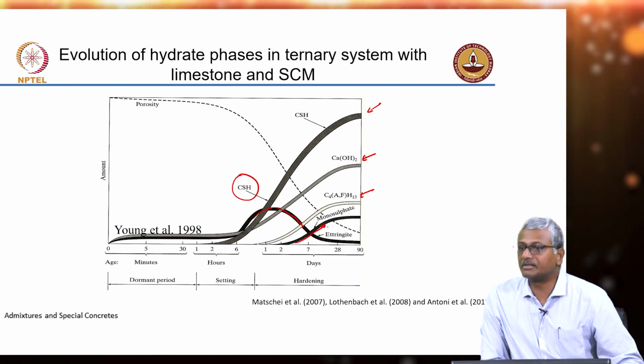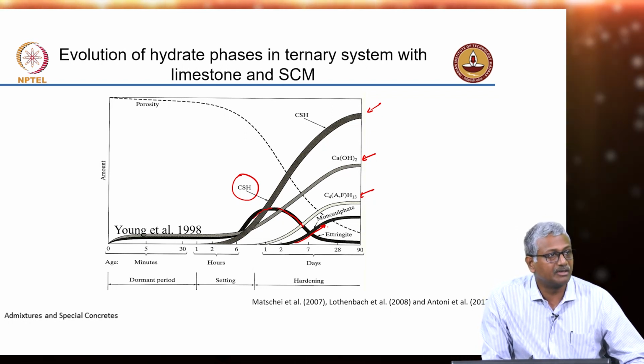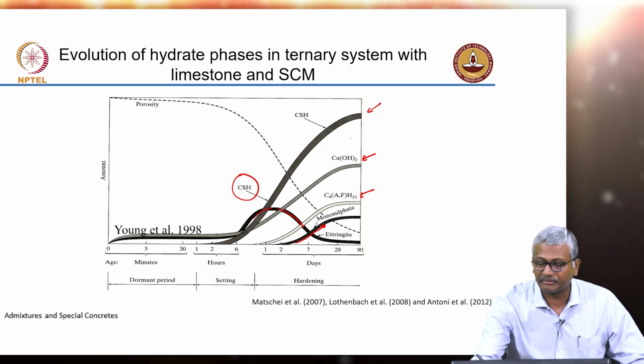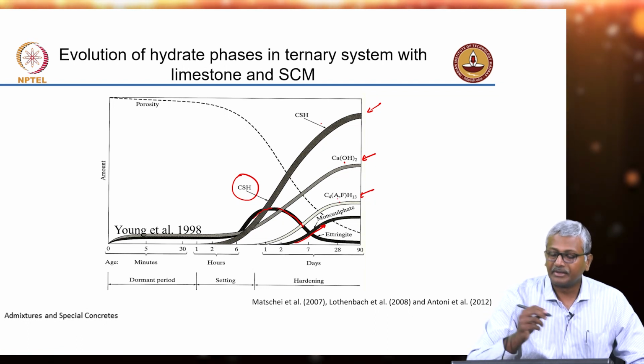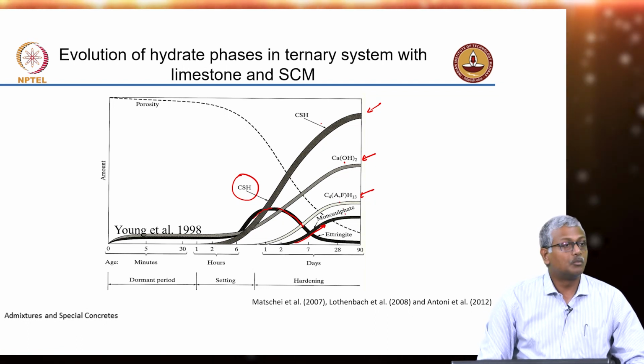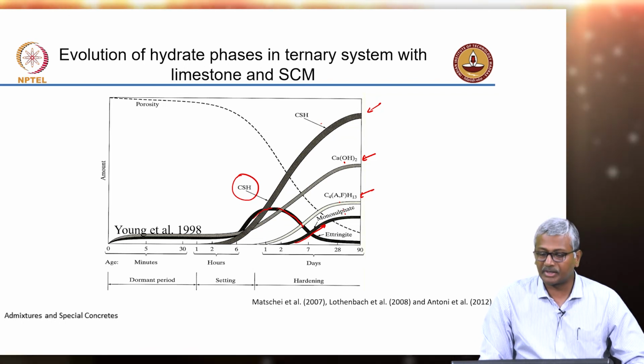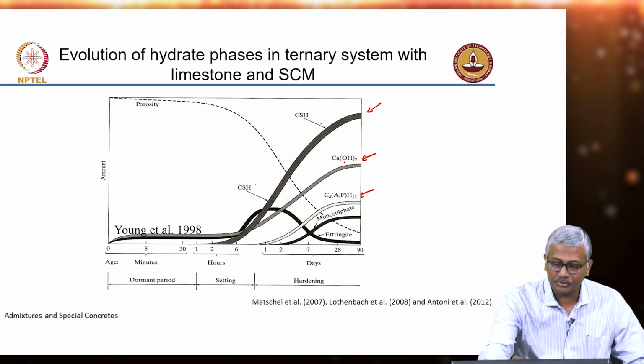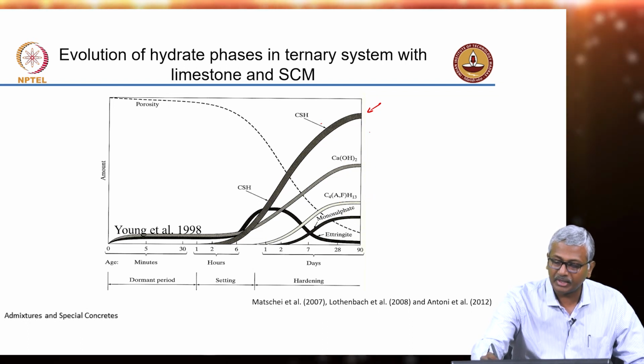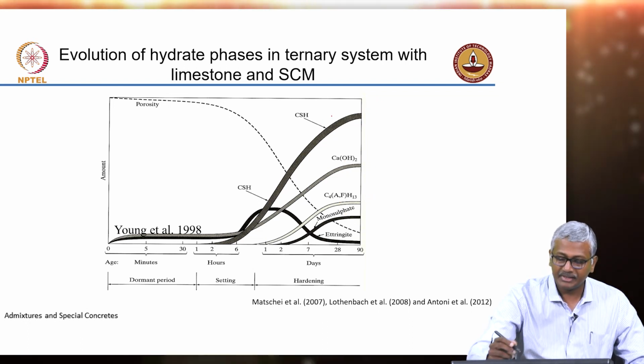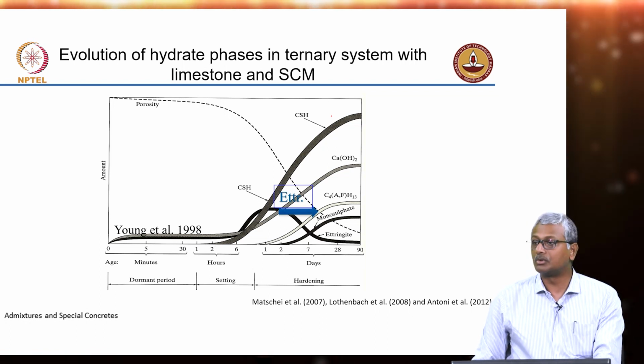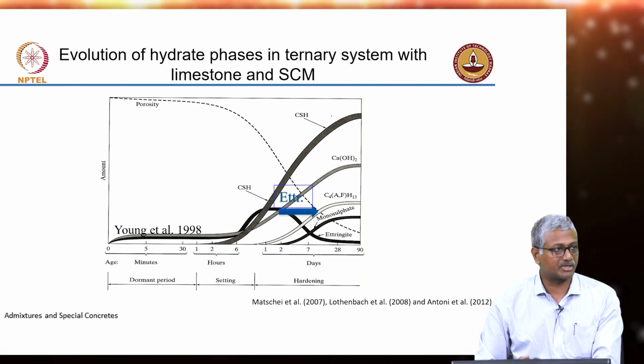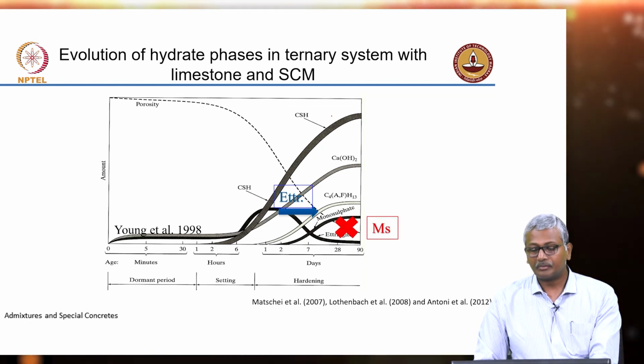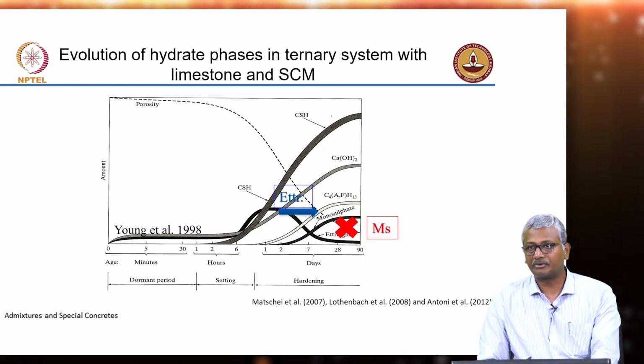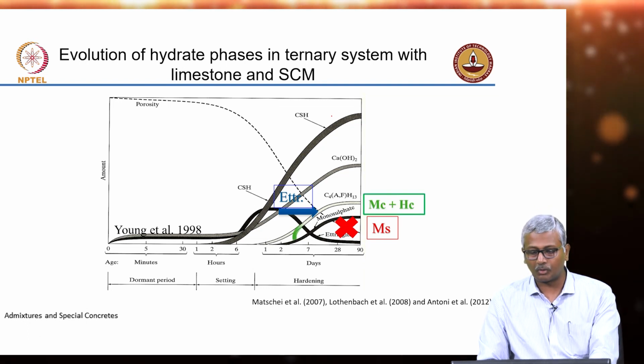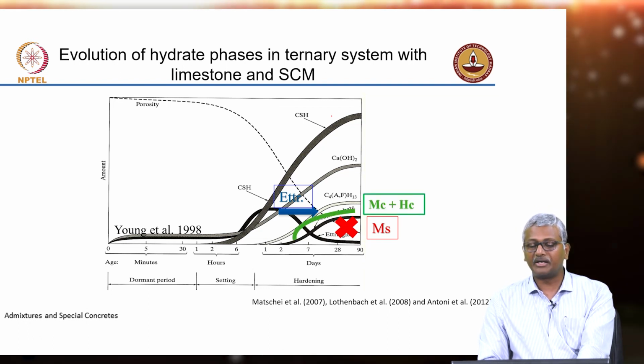Ettringite that starts forming at the early stages starts giving rise to monosulfate, and in the long term, the stable products are CSH, calcium hydroxide, calcium aluminate hydrate, and monosulfate in the long term for a plain Portland cement. So, what happens in the presence of limestone and calcined clay, or limestone and slag, or limestone and fly ash, is that you don't have this conversion of ettringite to monosulfate. So, ettringite remains stable, monosulfate formation itself is reduced or almost avoided. You start forming monocarbonate and hemicarbonate.